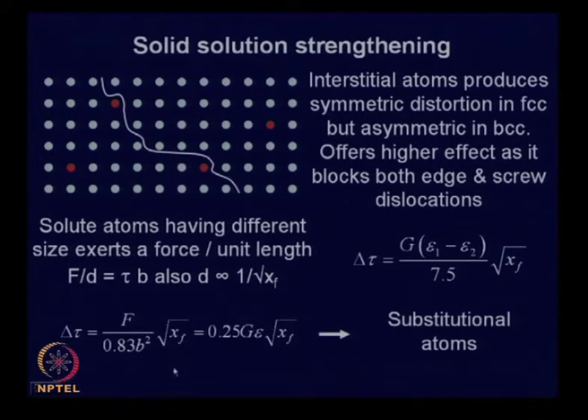Now, it is possible to find out how much force is exerted by the solute atom on the dislocation, and this force will depend on whether you have more number of atoms. What is more important is the force per unit length of the dislocation exerted by the solute atom. If d is the spacing between two solute atoms, then you can say this is the force per unit length, and to move the dislocation you apply a shear stress tau. In that case, the force on the dislocation will be tau b, and the two have to be equated.